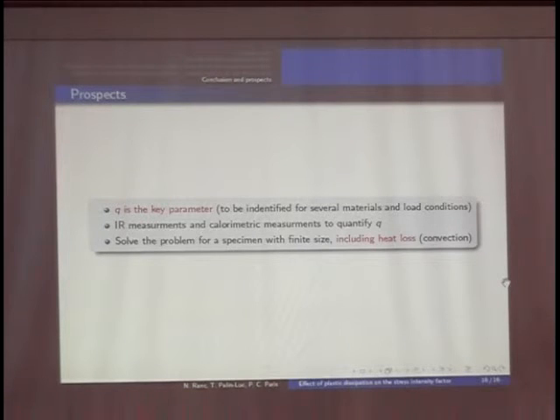This is more of a comment really, but it picks up on Sylvie's and Reinhold's point. The value that you gave was an applied delta K of 20 MPa root meters at 30 Hertz, and you said that gave 2 MPa root meters thermal effect. Well, you'll never do gigacycle high frequency at 20 MPa root meters, because the experiment would only last 10 seconds. So what you're going to do is come down in delta K, and if you come down to 10 MPa root meters, you've got a factor of 16, because it's to the power of 4. To the power of 4. So because you've got this very strong delta K to the 4th in there, I suspect you're not going to get significant effects at the kind of stress intensity factors that you run at relatively high frequency, and so probably for many practical situations the effect's going to be quite small. I'm not saying that there aren't situations where you might notice it, but I suspect...